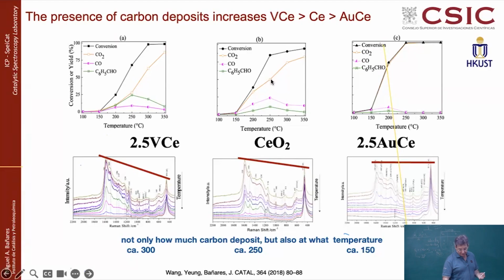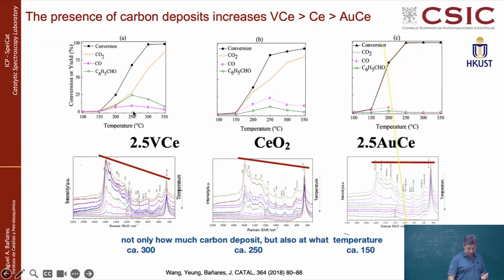Converting toluene quite okay, mainly to CO2, but you also get the yields to carbon monoxide and to benzaldehyde. So it's not a complete combustion of the toluene molecule. Now, if you are adding vanadium, the system becomes less active because this is combustion. So the production of CO2 is even lower. You are increasing the benzaldehyde, which is more appropriate of a partial oxidation reaction.